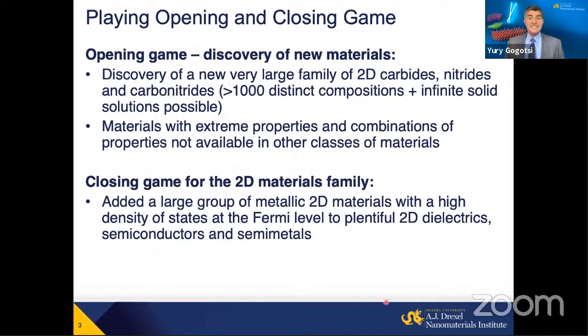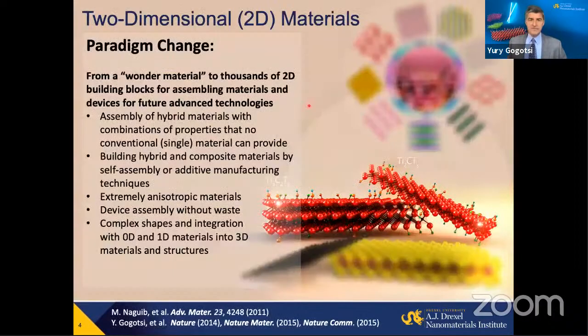But also they added something that was really missing in the 2D materials world. They added truly metallic materials with a high density of states at the Fermi level, with a high concentration of carriers to the world of 2D materials, which are mainly semiconductors, dielectric, or semimetals. Recall that even famous graphene is a zero band gap semiconductor, even though it's praised for its high conductivity in many cases.